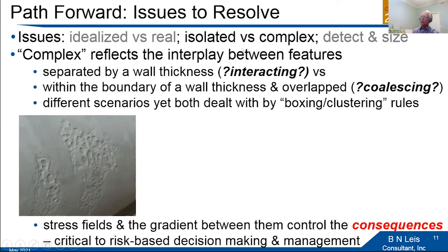Complex in this context refers to the interplay between corrosion features, and I have an example of 2 clusters of corrosion on a pipeline. It's a 24-inch diameter pipeline. You can see the bottom side of the pipeline here, top side's roughly in this vicinity. And isolated features, this cluster of corrosion is isolated from this cluster of corrosion by the full wall thickness. So we talk about this cluster interacting with this cluster because they are separated by a full wall thickness. So we use interacting in that context.